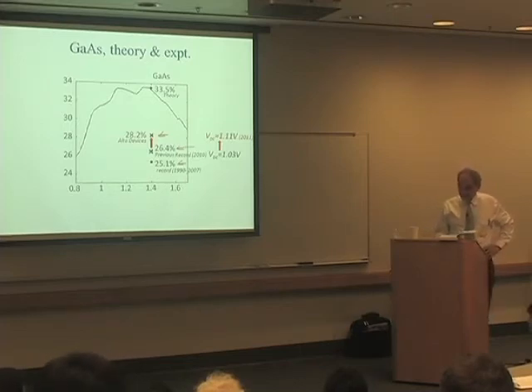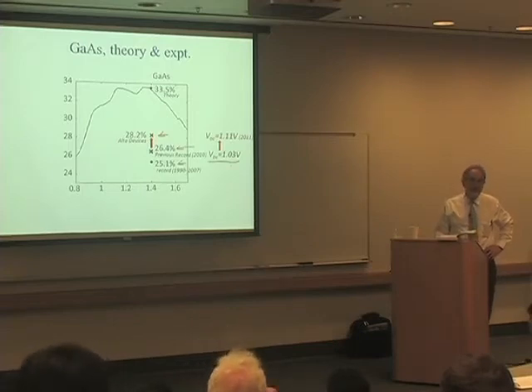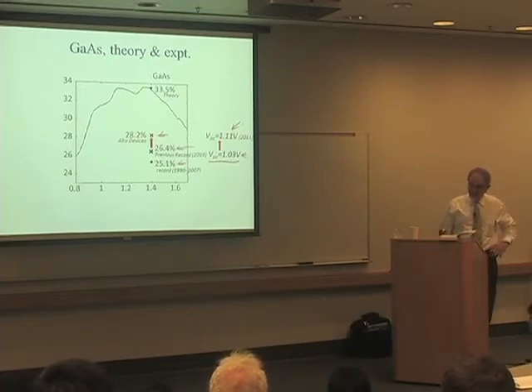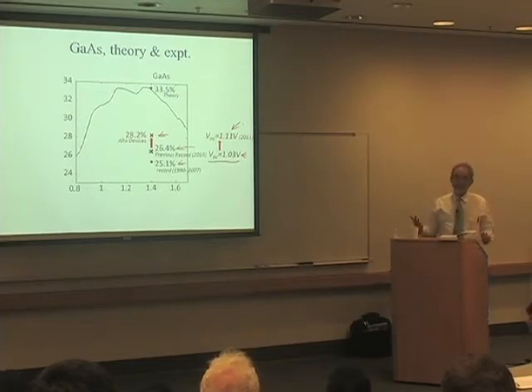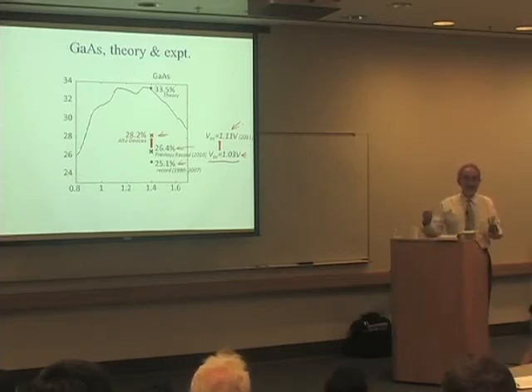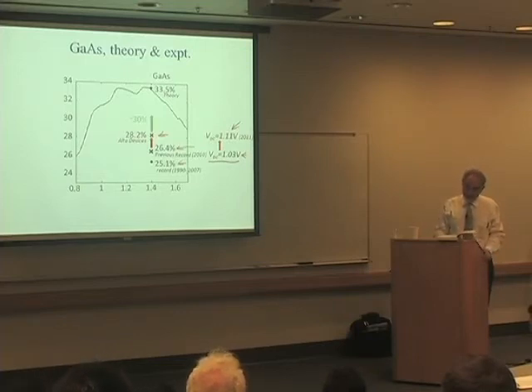And in fact, it's even more dramatic in terms of the open circuit voltage. A year ago, the record solar cell had an open circuit voltage of 1.03 volts. The new record solar cell, 12 months later, is 1.1 volts, 1.11, an 8% increase in voltage. So that's not just doing things better. That's actually changing the physics of the solar cell. The changed physics is to capture and recycle the internal photons, help them get out of the photovoltaic material. And so we're in a new regime of really high efficiency. And where this is headed, it's not much of an extrapolation to say we're going to get to 30% efficiency, and then things will slow down because we're reaching the theoretical limit. So this is really quite outstanding for a single junction flat plate cell.